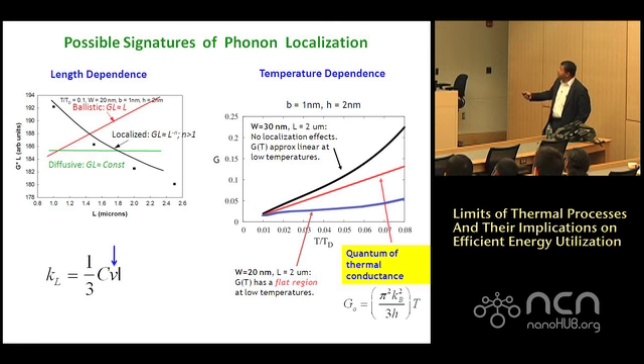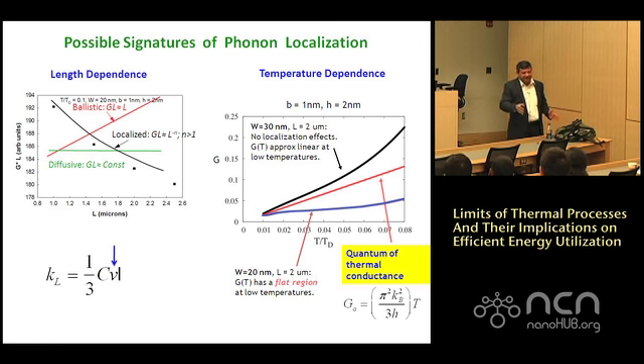If it is ballistic transport, the thermal conductivity increases as a function of length because conductance is constant. But if it is localization, the thermal conductivity will decrease with localization. If you find a sample, or a collection of samples, where the thermal conductivity of the material decreases with increasing length, I don't know of any other reason but localization. But no one has ever observed this.